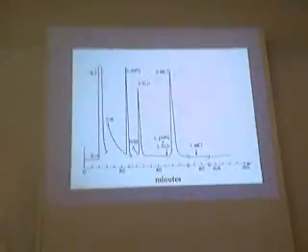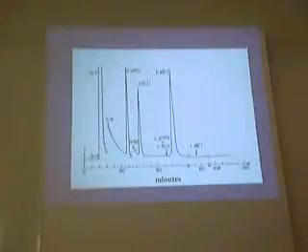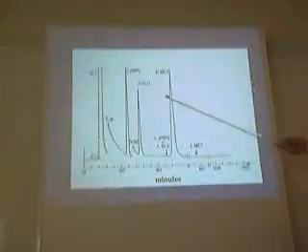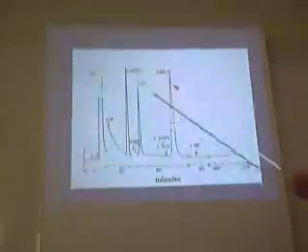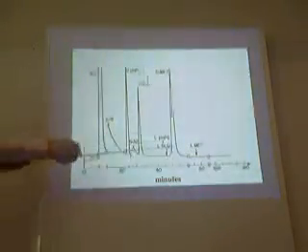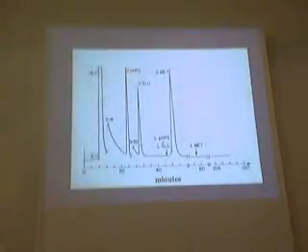If you now take the crystals which have been grown at the surface, either at the glass-water surface or at the air-water surface, and you analyze, in this case we used, for representation, para-hydroxyphenylglycine, glutamic acid, and DL-methionine. You can find that if you grow the crystal of glycine at an interface, the crystal grows unidirectionally into the water and picks from the feedstock only, in this case, the D-amino acid, depending on the orientation of the crystal at the air-water interface.